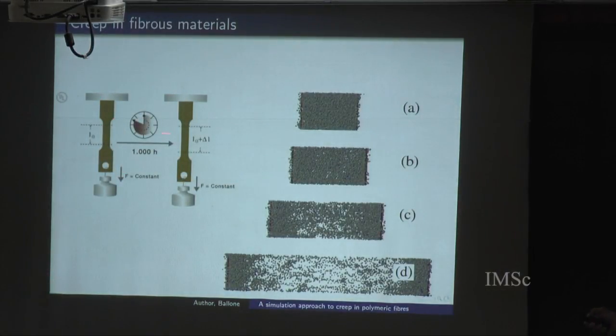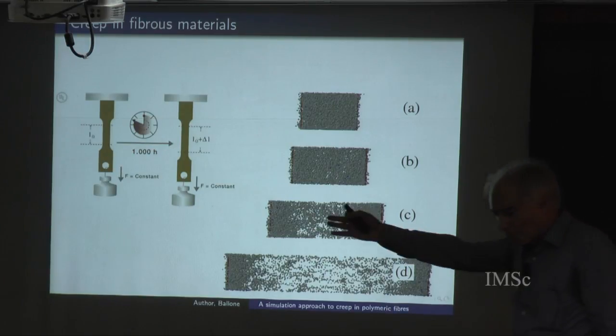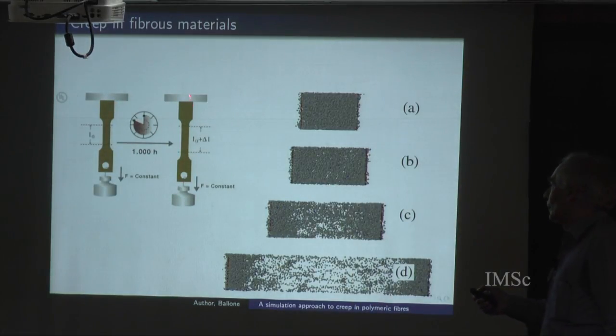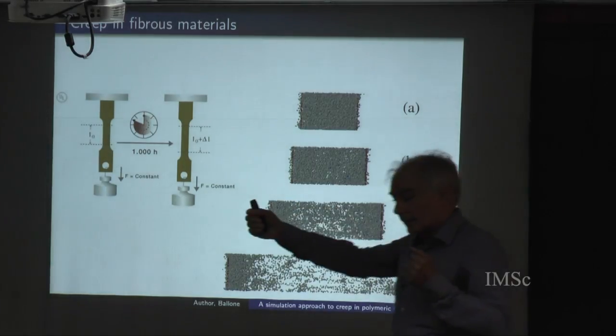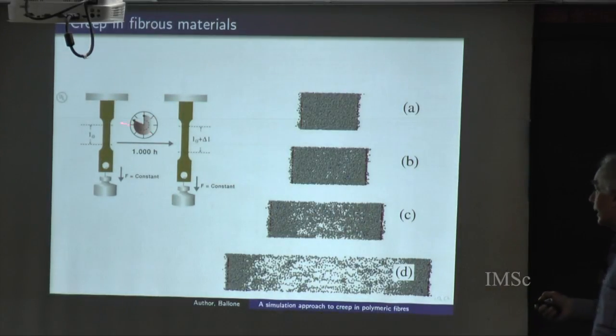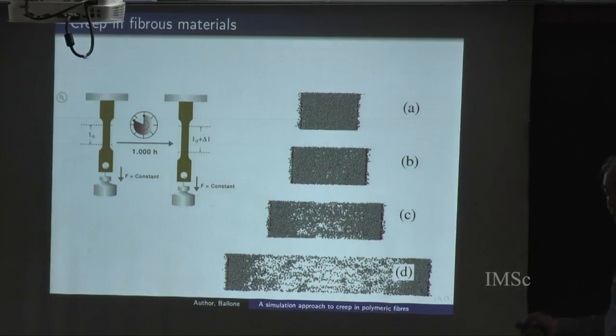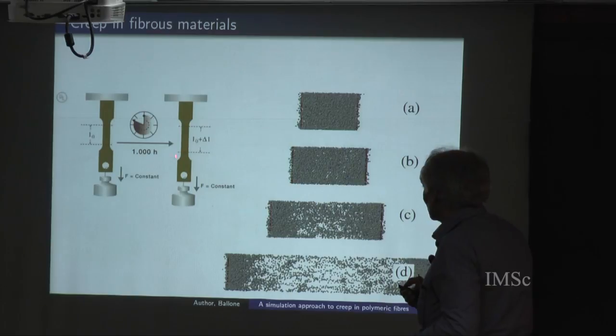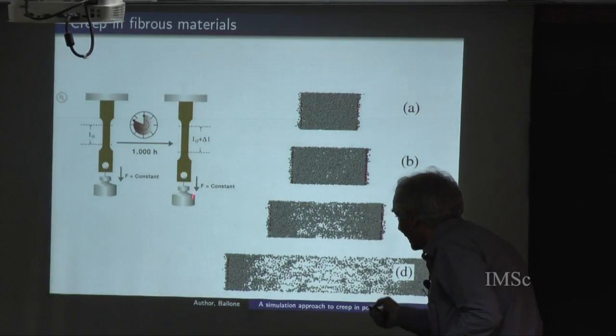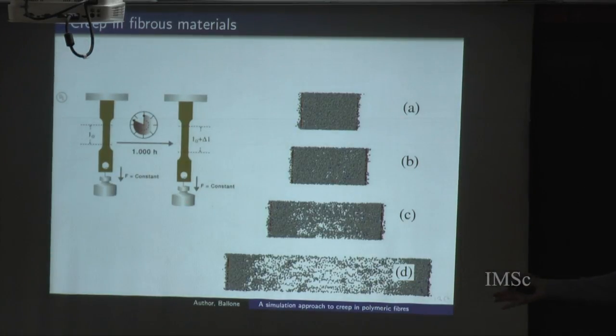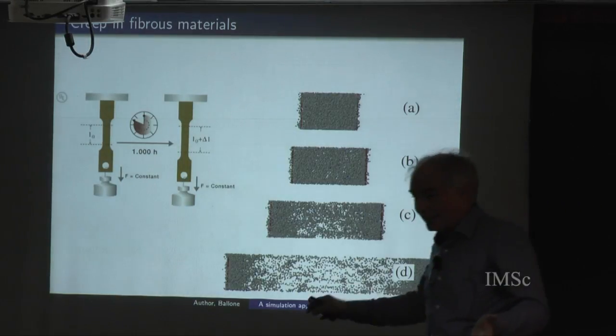So you keep the load slowly over macroscopic time scales. You will notice that the sample is changing shape and dimensions. And so this is the typical behavior of a ductile material. Eventually it will fail by creep. Not because it became mechanically unstable, but because essentially a system under stress is intrinsically unstable, as we have been reminded 2 days ago. Eventually, there is so much divergent free energy in moving this piece away that we have to go there, at least by thermal fluctuation. So if a system has a finite temperature, it has to break, no matter what.